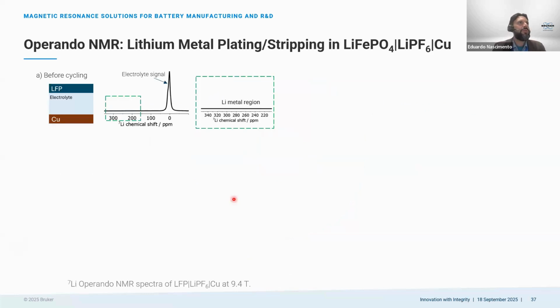I will try to speed up. So here is an example of the operando NMR. Now remember, you have your cell inside the NMR probe. So this is a spectrum of your whole battery cell. In the beginning, before the cycling, you can only see the electrolyte signal here because we are focusing on this lithium analysis. So in this window of analysis, you don't see any lithium metal in this region.